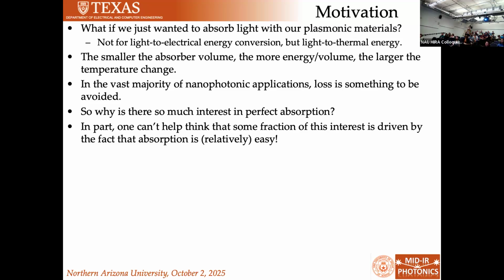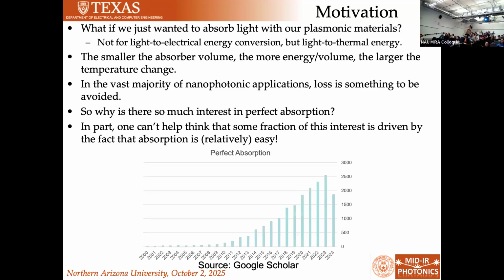But there's a huge field of literature, and you can find this if you do a simple Google Scholar search for it, on perfect absorption. Now, I have a sort of cynical view as to why that is the case, because if there's one thing it's really easy to do when you're trying to make a new material, it's get it to absorb light. It's actually usually what you're trying to avoid. Loss is what you're trying to avoid. But you make a new material, it absorbs a lot of light. It's not what you wanted, but you can call it a perfect absorber and you can get a paper out of it, right? And it's approximately done 2,000 times a year now.